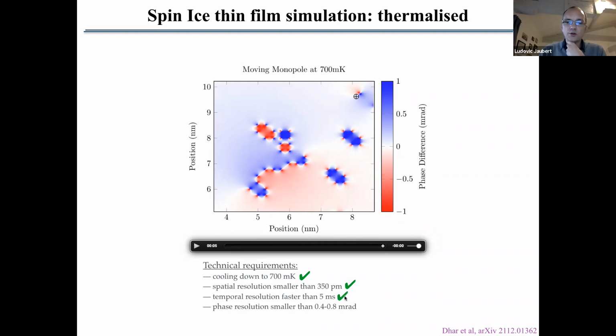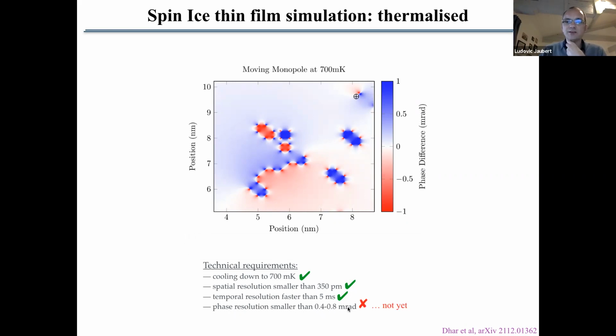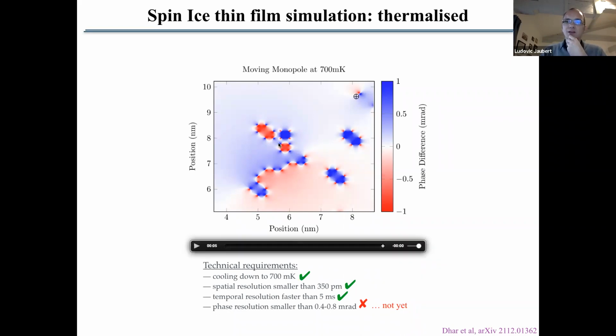A temporal resolution of 5 milliseconds at least, that's also possible, but a phase resolution of 0.4, 0.8 millirad, that's not there yet. Right now, I think the best microscopes are more like around maybe 2 millirad, maybe it goes down to 1, but it's not there yet. So we still need one more technological step, and to include a dilution fridge in the TEM to be able to realize experiments. But that's not an order of magnitude difference. That's something that is probably possible in the future.